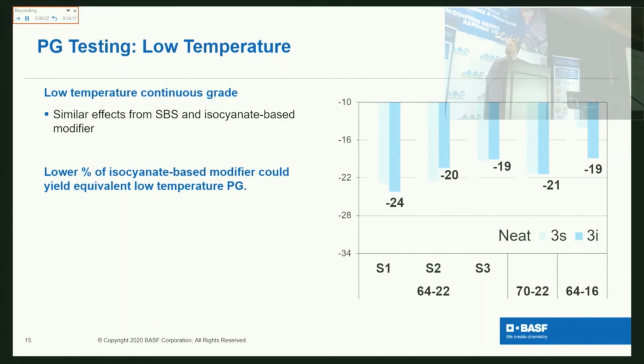We also looked at the low end, what happened to it with the different SBS and isocyanate. Again, we found that a lower dosage of an isocyanate-based modifier could yield equivalent results to low temperature as an SBS type modification. It's very similar in effect when it comes to stiffening the material or moving your PG grade, with the exception of being reactive. So some asphalts will react much more.